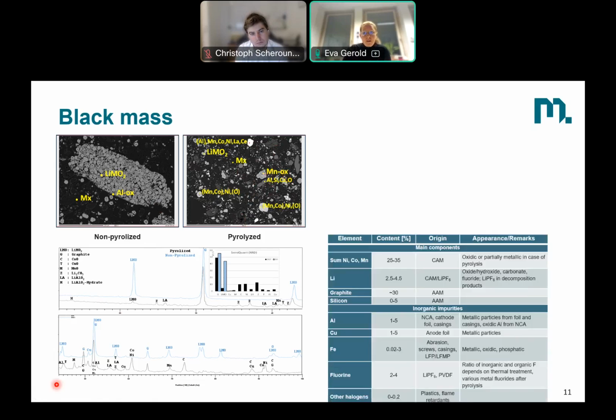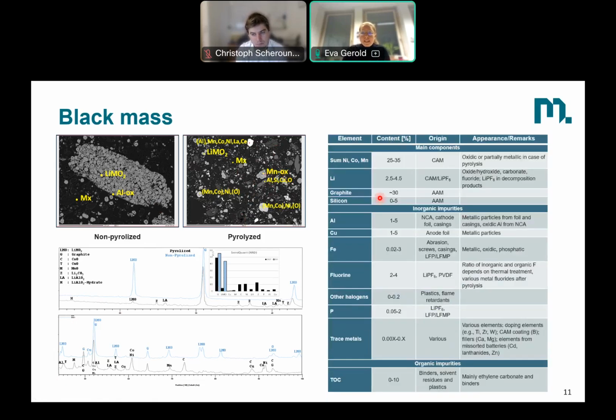And if we have a look at the composition, we can see here at the upper side of this table the sum of the cathode and anode active materials, so nickel, cobalt, and manganese, and lithium, and graphite and silicon from the anode side, of course based on an NMC chemistry battery. But then the bad boys are coming, so the inorganic and the organic impurities.